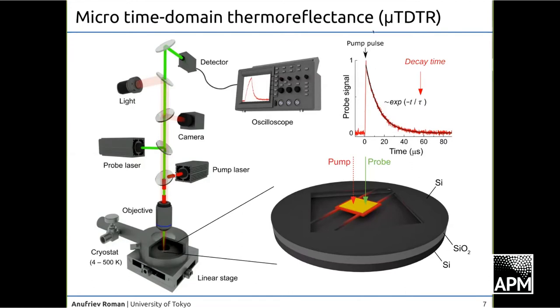So by monitoring this curve, we're fitting it with an exponent. We can basically measure how quickly heat spreads through the nanowire that we want to measure. And this gives us the thermal decay time, tau. It's a very important quantity. It means the longer the time, the more resistive is our wire. The shorter the time, the faster heat can spread, okay?